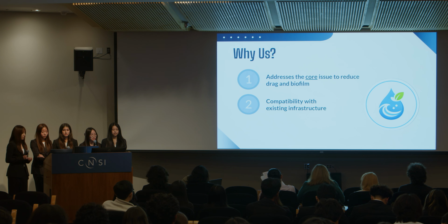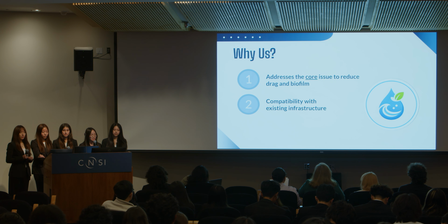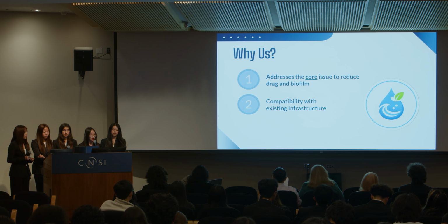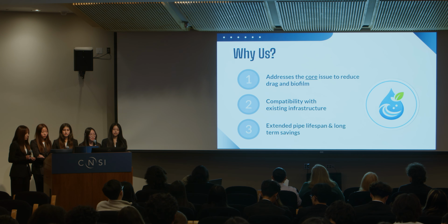Another major advantage is that SharkPipe is fully compatible with existing municipal materials and manufacturing methods. The pipe uses standard UPVC, and the riblets are formed through microstructured extrusion, a scalable process already used in the industry. Additionally, the Zwitterionic additives are blended directly into the PVC, meaning that the anti-fouling function is permanent, not a coating that wears off. Together, these features make SharkPipe practical to manufacture, easy to integrate, and capable of delivering long-term savings through lower pumping energy, reduced maintenance, and extended pipe lifespan.